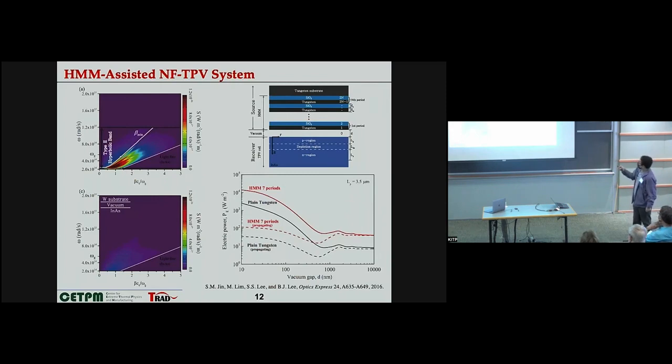So we consider metallodielectric multilayers, which you can also consider as hyperbolic metamaterials. Each metal-dielectric surface can have plasmons, and since the metal thicknesses are very thin, all the modes are coupled together, and some of the modes appear in a much smaller beta range, on the order of less than 10. Previously, the beta value was on the order of 50 to 100 times the magnitude of the vacuum wave vector.